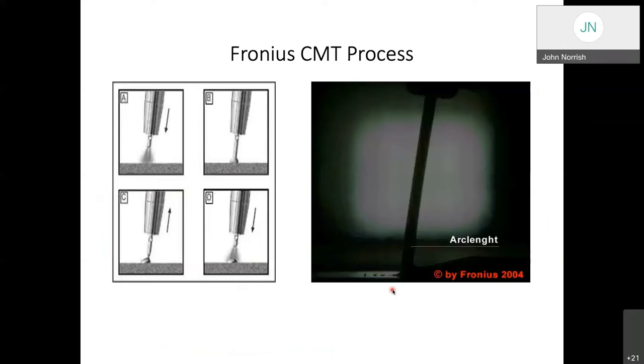Coincidentally, at the same time, we were working in parallel with a commercial company, and we didn't really know what was happening, but Fronius developed an almost identical operating system for completely different reasons. And as the pictures on the left show, it used the same principle. The wire was fed towards the plate during the arcing period. When the short circuit occurred, the wire was retracted very quickly, and then the arc was re-established.